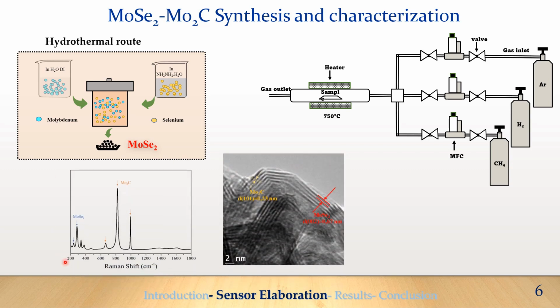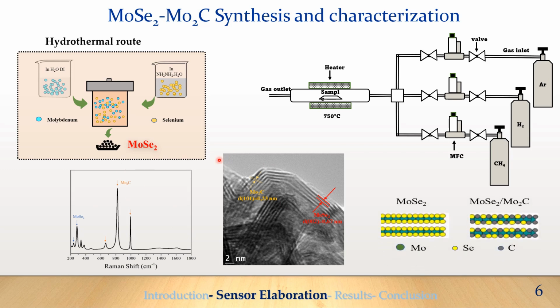The characterization by Raman spectroscopy and high-resolution transmission electron microscopy confirmed the formation of Mo2C on the surface of MoSe2. In fact, MoSe2-Mo2C forms a nanoscale heterostructure within the carbonized MoSe2.